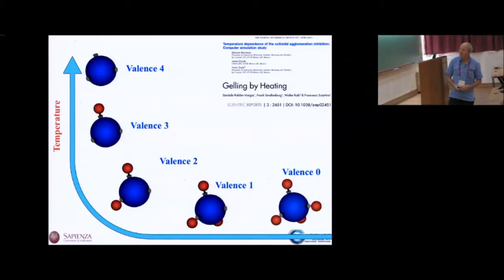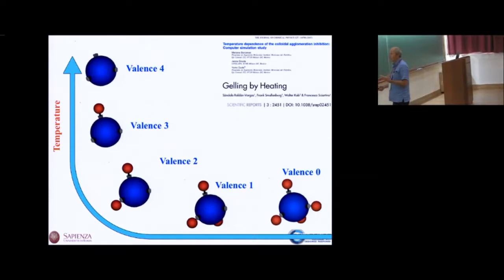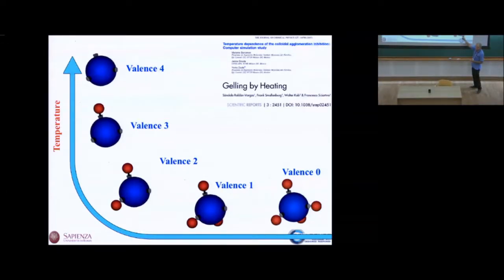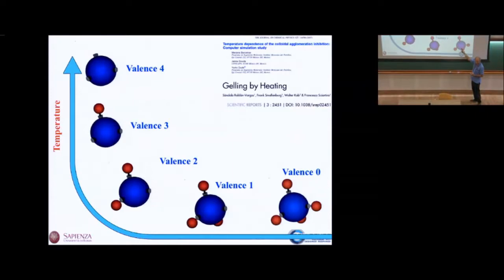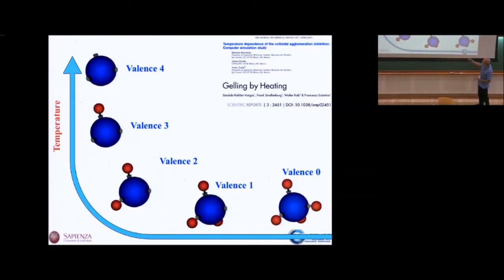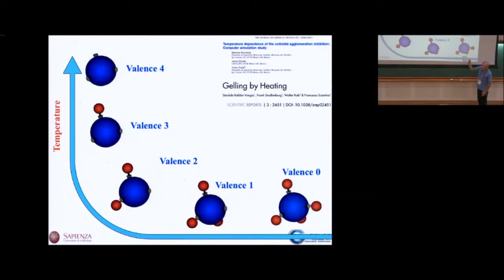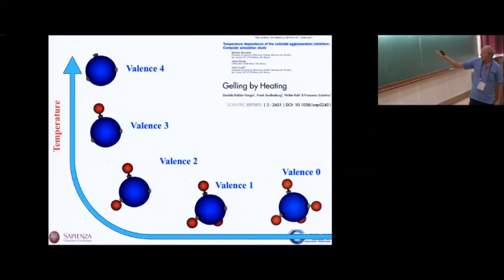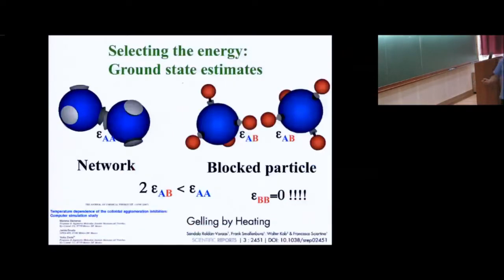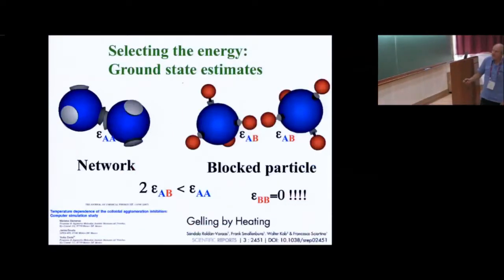So I have to find a way of attaching those particles, red particles that cap the bonds, as a function of temperature, in such a way that at low temperature, this is going to be the stable phase, right? The ground state. Because I want, at low temperature, to have a valence of 0. So for sure, I can play with the energy of the interaction between the red and the blue particle, make it stronger than the interaction between blue and blue, and make sure that at low temperature, this is going to be the ground state. Like in the Safran model, the dipolar chains are the stable ground state.